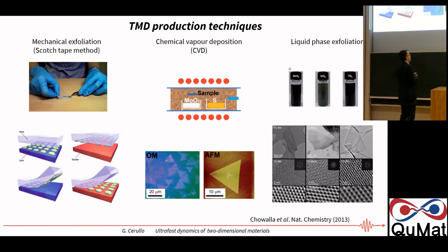And then you can also have liquid phase exfoliation, where you can make so-called inks of this material. So you start from the bulk, and by doing ultrasonication, you can exfoliate maybe not single layers, but mixtures of multi-layers, but then you can make really large amounts of these materials. You can make so-called inks, which have many technological applications. So you can make these materials by several techniques.